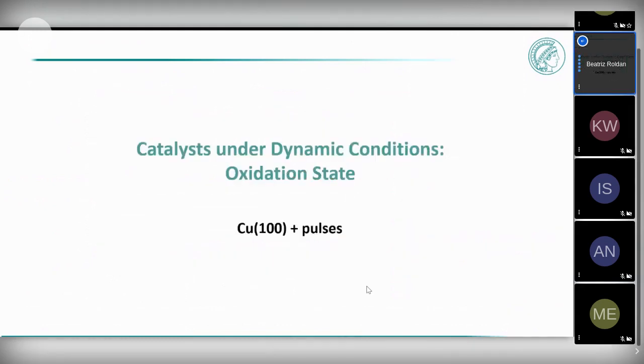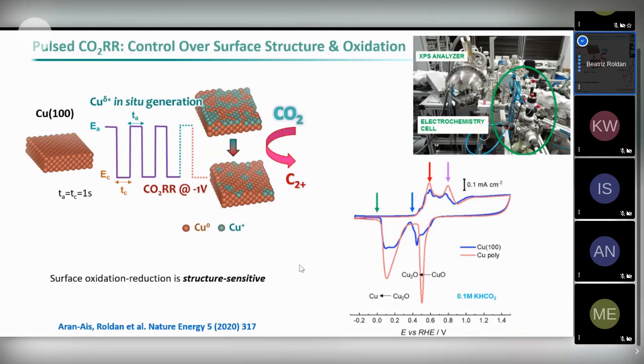So in the last part of my talk, I want to show you that we learn a lot about these 100 structures. They favor the production of hydrocarbons, and we decided to see, can we actually have these structures as a single crystal, and maybe we can pattern it, and maybe we are able also to stabilize a mix between metallic copper and copper plus. If you follow the literature, there have been indications that if you have a surface in which regions of metallic copper and copper plus, copper 2O, coexist under CO2 electroreduction conditions, maybe you favor the production of C2, C3 products. So we wanted to see this, and we use a single crystal to start to do this reaction, copper 100, and then we apply pulses.